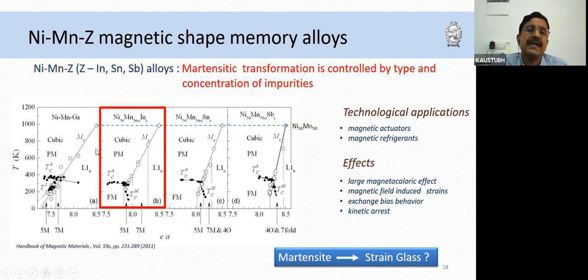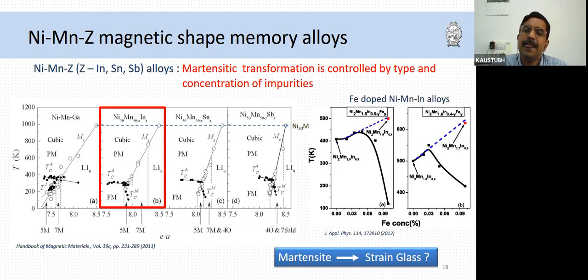and we thought we should concentrate on one system, that is nickel manganese indium. And there is a critical concentration, so we wanted to be a little bit far away from this critical concentration, and we wanted one impurity which would most definitely suppress the martensitic transition. So in literature, iron, or Fe, when doped in most of these alloys, any of these systems, suppresses the martensitic transition temperature, and this is a well-known fact.